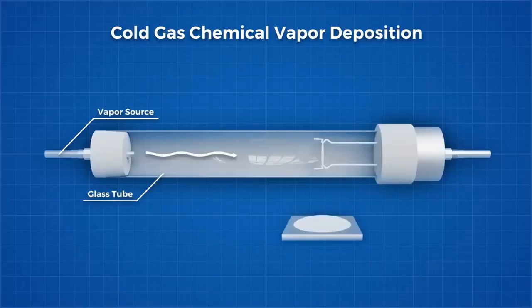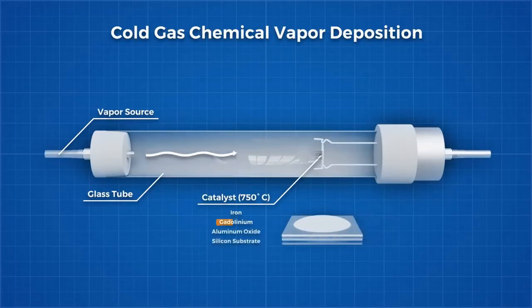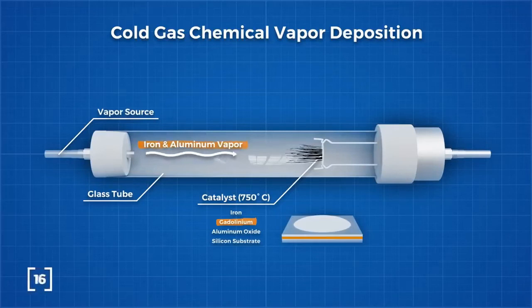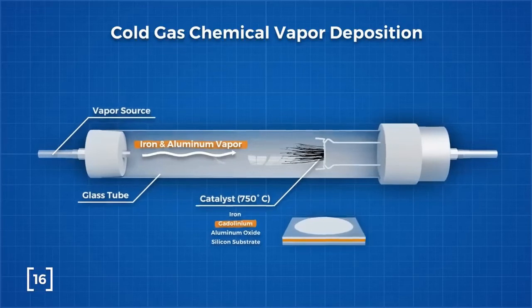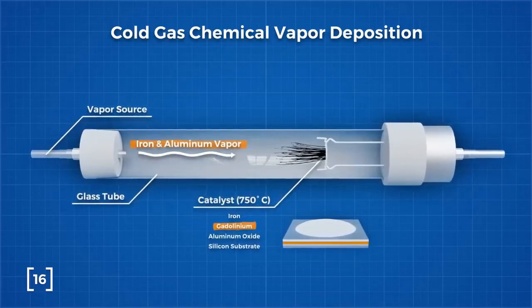26 hours. They did this by adding a layer of gadolinium to a conventional iron aluminium oxide catalyst coated on a silicon substrate. Then, using a lower chamber temperature, small concentrations of iron and aluminium vapor were added into the chamber. These factors combined managed to keep the iron aluminium oxide catalyst active for much longer. This method is a major leap forward that could allow carbon nanotube products to begin entering the market. But we are still a long way from a space elevator.